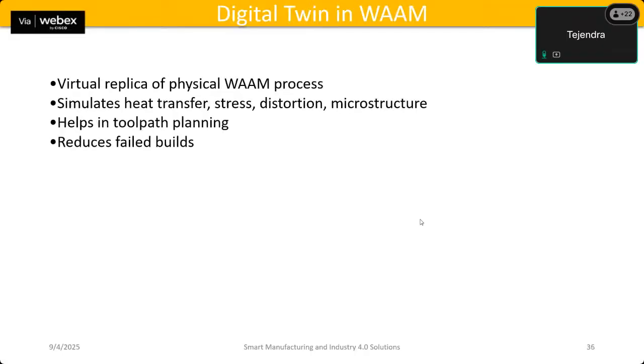The digital twin could be another key element of smart manufacturing applied to WAM. A digital twin is essentially a virtual replica of the actual WAM process. It allows engineers to simulate the heat transfer during the deposition, so that it can predict how heat will accumulate and where the residual stresses might be formed. This is important because too much heat can cause distortion or cracking. The digital twin also helps in predicting the mechanical stress, the distortion, or even the microstructural evolution, or if any correction in the microstructural evolution is required, we can find or predict it through the digital twin.